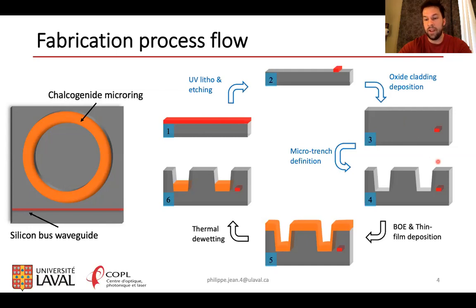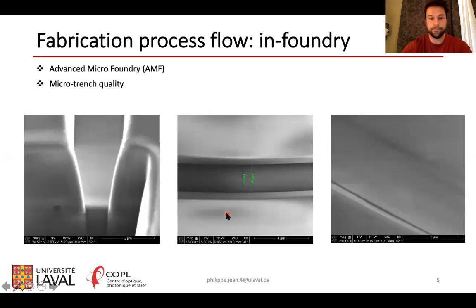And we have an additional step where micro trenches are etched inside the top cladding to define the chalcogenide waveguides. Next, at COPL, we did a short HF acid dip, and we did thin film deposition of the chalcogenide. And the final step is a thermal dewetting process. So the chips were fabricated at Advanced Micro Foundry, or AMF, in Singapore.